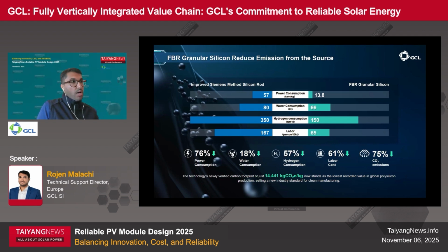Here we want to show how FBR granular silicon significantly reduces emissions and resource consumption compared to improved Siemens method. You see the power consumption, water usage, hydrogen consumption, and labor costs are significantly down. Most importantly, the CO2 emissions are reduced by 75%, setting a new benchmark for clean manufacturing. The technology achieves a verified carbon footprint of just 14.4 kilogram carbon equivalent per kilo of product. This is the lowest recorded value in global polysilicon production, establishing a new industry standard for sustainability.